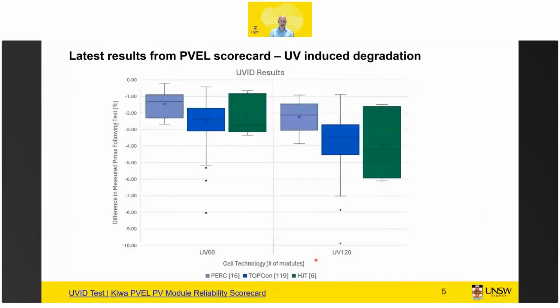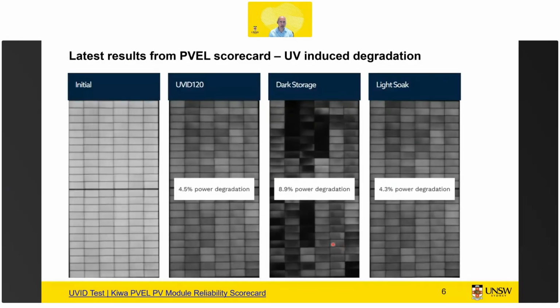Of course, the hot topic at the moment is UV-ID, where we see that PERC, TOPCon, and heterojunction technology all have sensitivities. And for TOPCon, we see outliers which are really scary, with like 10% reduction after UV 120. So that's 120 kilowatt hours of UV, which sounds like a lot, but that's a little over 2 years in Sydney, where I am. So definitely not 25 years. And I will get back to that as well.